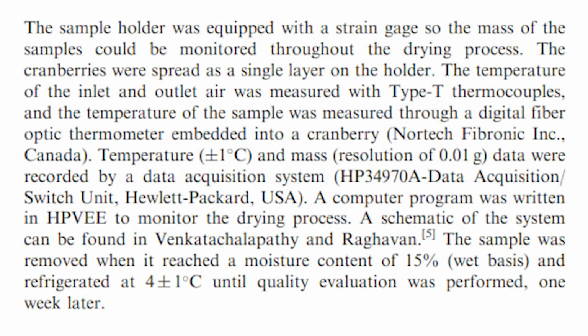The sample holder was equipped with a strain gauge so the mass of the samples could be monitored throughout the drying process. The cranberries were spread on a single layer on the holder. Temperatures of the inlet and outlet air were measured by Type T thermocouples, and the temperature of the sample was measured through a digital fiber optic thermometer embedded into a cranberry. Nortec Fibronic Inc., Canada. Temperature, plus or minus 1C, and mass resolution of 0.01 grams.